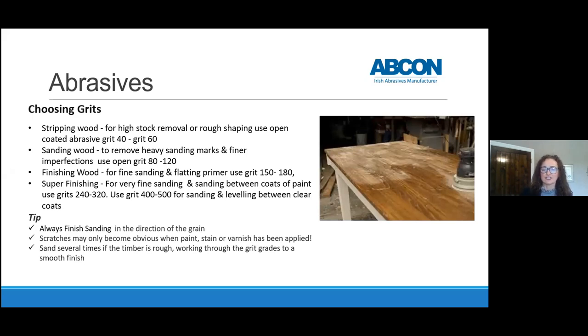And for super finishing or very fine sanding, and sanding between coats of paint, you might go as fine as 240 or 320, and as fine as 400 to 500 for sanding and leveling between clear coats. When you're finishing, you always finish sanding in the direction of the grain. The scratches may only become obvious when the paint, stain or varnish has been applied. And you might sand several times if the timber is rough, working through the grit grades to a smooth finish.